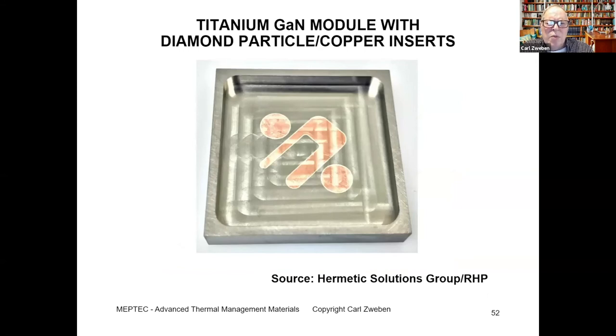It's made of titanium, which has a low coefficient of thermal expansion, but also low thermal conductivity. So in regions of the package where we need high thermal conductivity, diamond particle reinforced copper has been used as inserts. And this is a good example of using an advanced thermal material where you really need it. And it's especially significant when the material is fairly expensive, as diamond particle composites are at the present time. But this package is, as far as I know, in serial production.